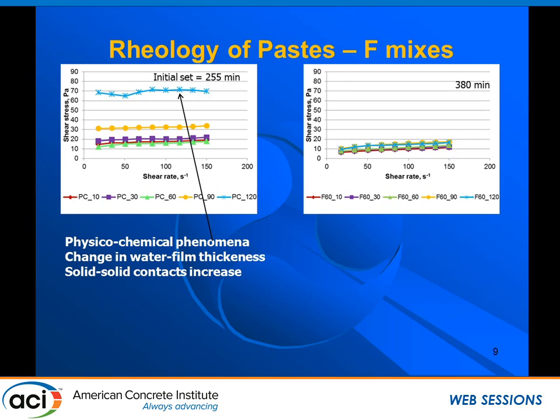For the PC mix, so here we have PC 10, 30, 60, 90, and 120. For the PC mix, although we went only up to 120 minutes, so not close to the setting time, we already see something going on. At 90 minutes, we see a change in the curves. What's happening here is that the water film thickness around the cement grains is changing, so the solid-solid contacts increase.